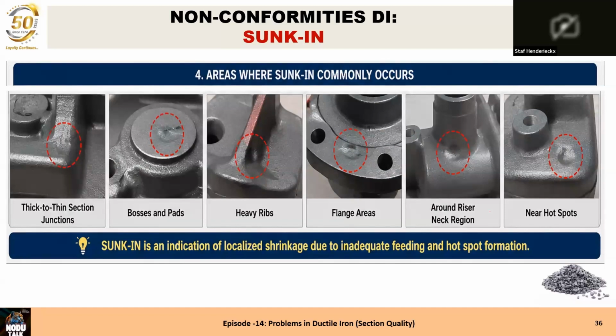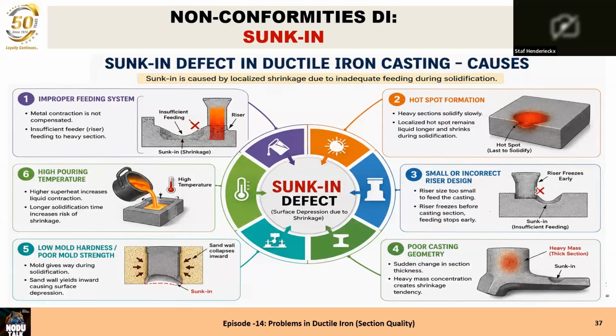I saw it very few times, and then near a hotspot. It's an indication, if you see it, that localized shrinkage is not being fed by the riser at the moment of solidifying. It's an improper feeding, of course. It's always about feeding. Every porosity is about feeding. A high temperature can also be a reason, because then total shrinkage can be much more than expected. A low mold hardness, again, due to the expansion during solidification, it's possible that we have an extra volume.